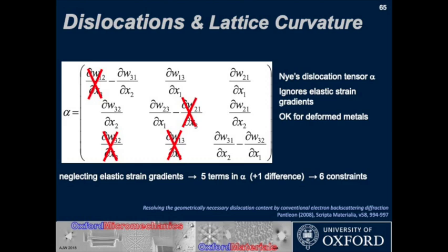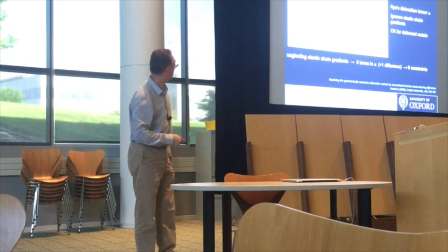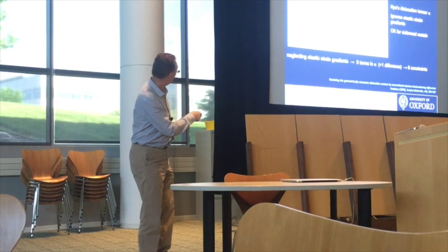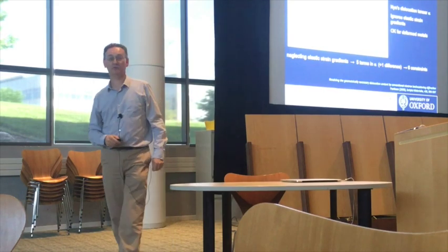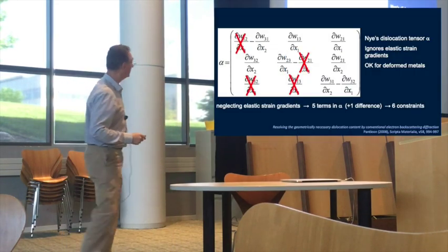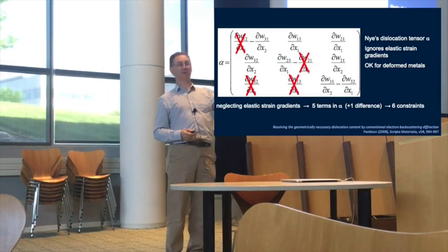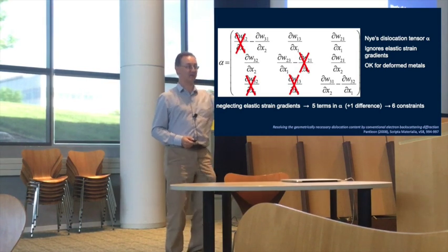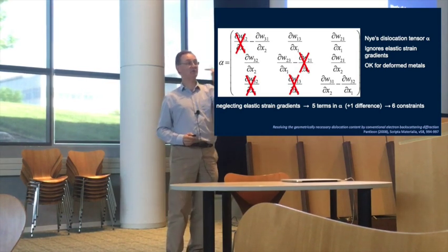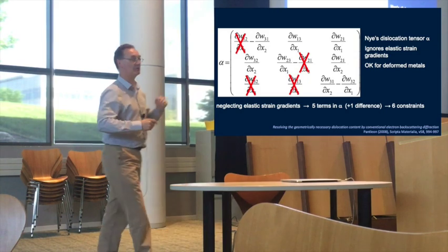And because of the different symmetries, the different makeup of those two terms, there are actually rather more terms accessible if we just think about the 9 terms. So actually there are, well, it looks like when you look at this, there are 5 terms, but actually these 2 in here, you can also look at the difference between those 2 terms. So there are 6 things that are recoverable in here, which makes sense. You're making rotation measurements around 3 different axes and how they vary with 2 directions on your map, so there should be 6.